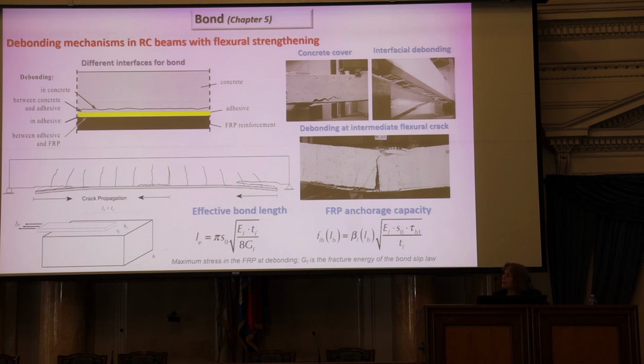Okay, so these are typical expressions that you will find in Bulletin 90 regarding the effective bond length and the FRP anchorage capacity at the end. You may also have the same phenomena happening near interior cracks. You may have the beginning of the delamination near an interior crack.